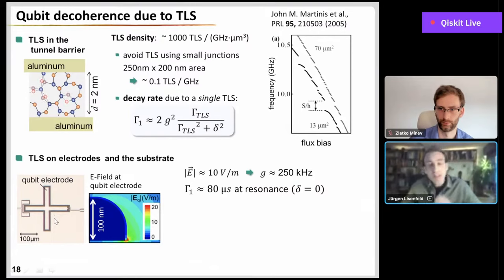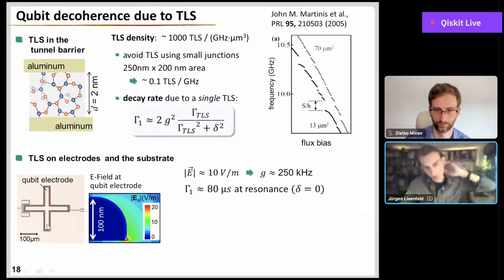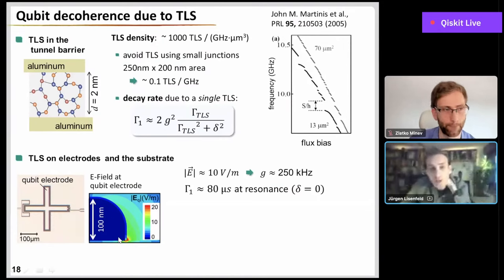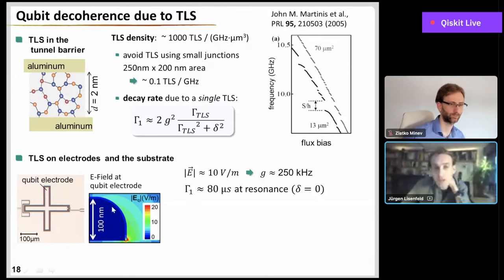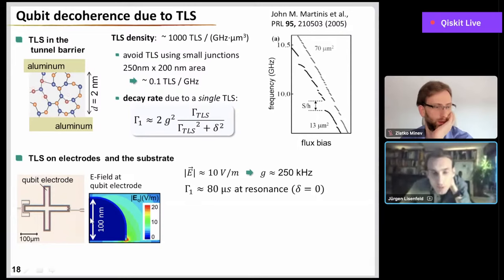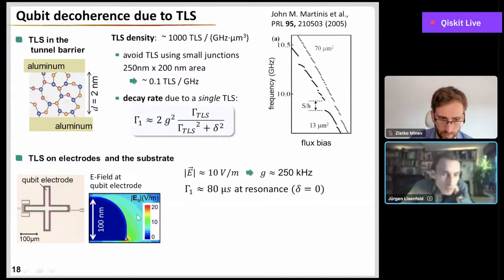So we can just estimate again the coupling strength of such a defect somewhere here at the edge of this qubit electrode to the qubit, simply by estimating the electric field strength here. This is done here in a simulation where we plot the amplitude of the AC electric field due to the qubit plasma oscillation mode. And you see that this field strength can reach up to 10 volts per meter here at this edge of this qubit electrode. There's of course a hotspot here where this qubit electrode touches the substrate. There the fields are a bit larger, but let's say 10 volts per meter is a good average value.